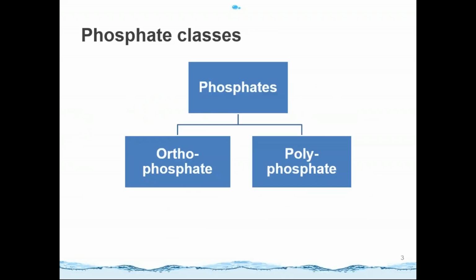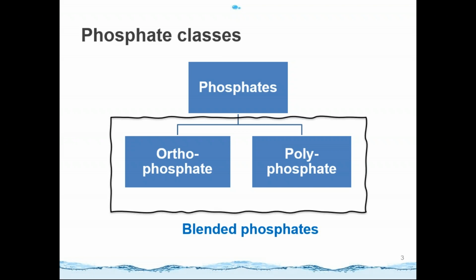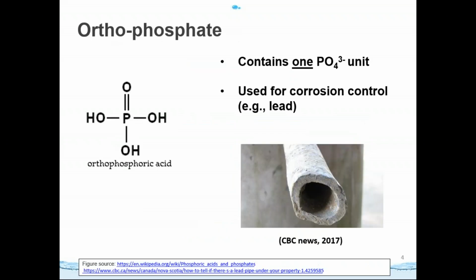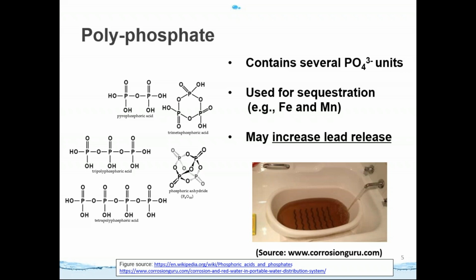When we talk about phosphate, in general it can be divided into two categories. The first one is orthophosphate, and the second one is polyphosphate. But in commercial products, we call it blended phosphate. Orthophosphate contains only one orthophosphate unit. It is commonly used for corrosion control. Polyphosphate has a lot of different species, and it contains several orthophosphate units. It's usually used for sequestration to solve the color or turbidity problems caused by iron and manganese. But the disadvantage of using polyphosphate is that it may increase lead release through complexing lead with the polyphosphate molecule.